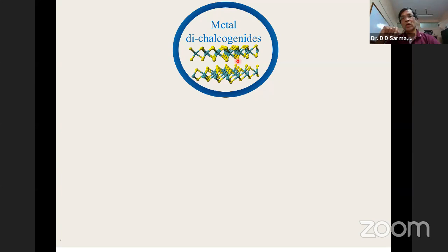What is the metal dichalcogenides? By the formula, it's something like MX2. It's a metal M and two of the chalcogen X. So MX2 is the typical formula. You have the metal layer hexagonally arranged in the central layer, and there's a sulfur layer on top and a sulfur layer below, making it MX2. This is the monolayer unit consisting of three atomic layers, and they're separated from the next layer by a van der Waals gap, making these essentially 2D, even when you have a bulk system, because the bulk system consists of these 2D stacks, one on top of the other.